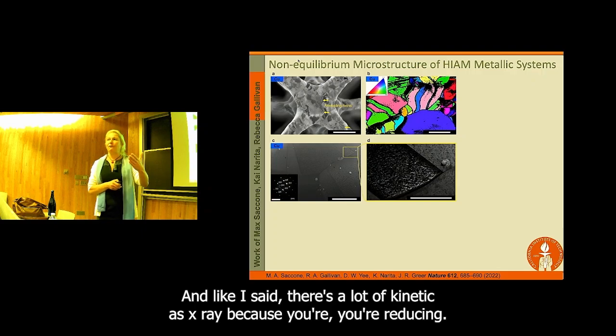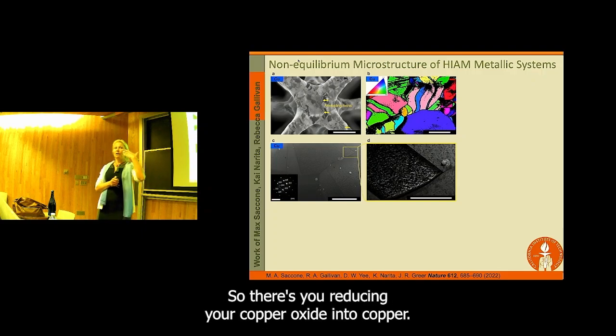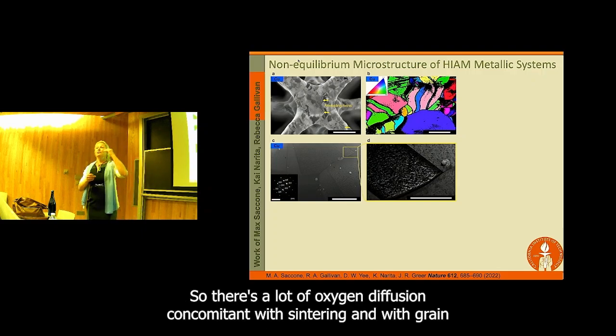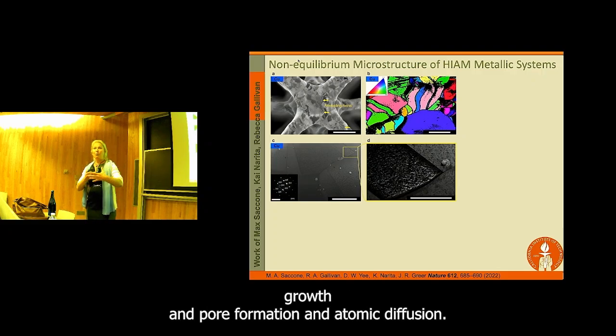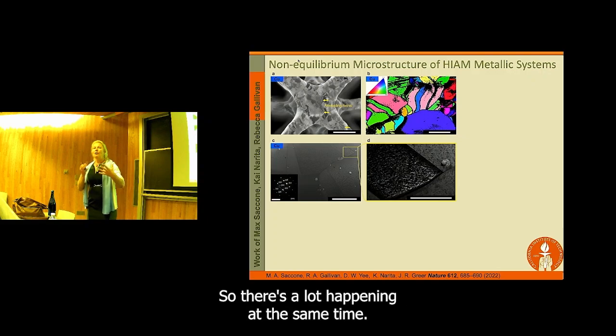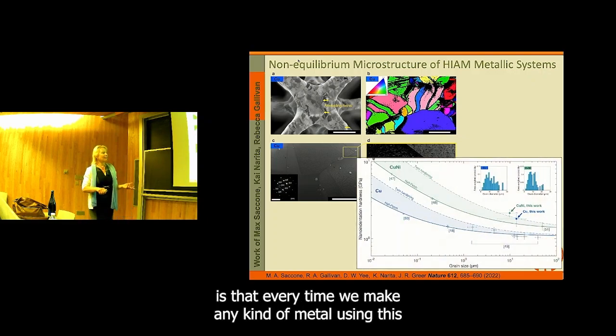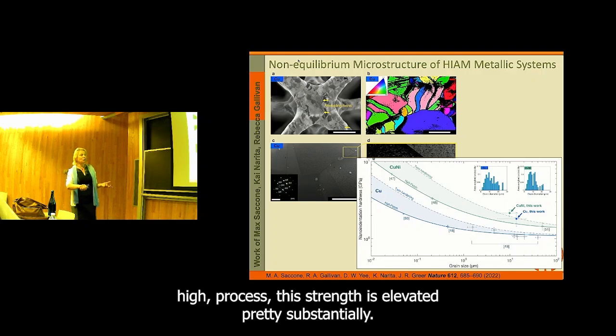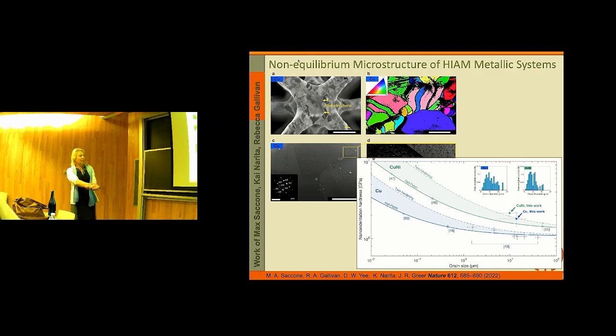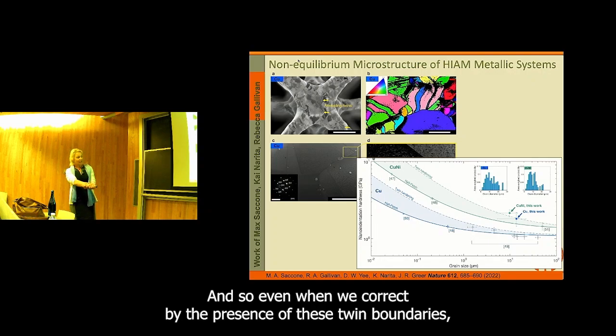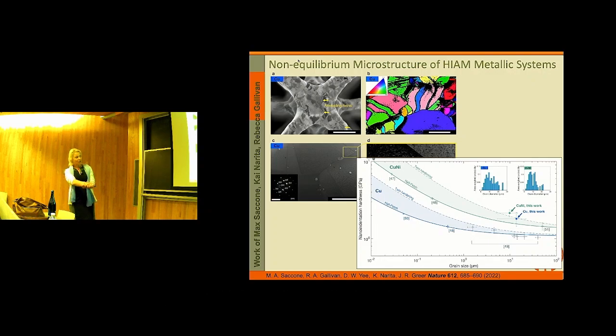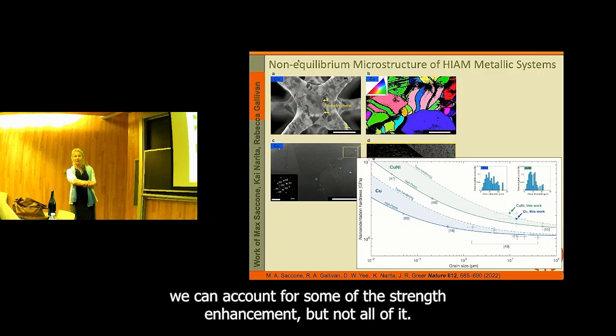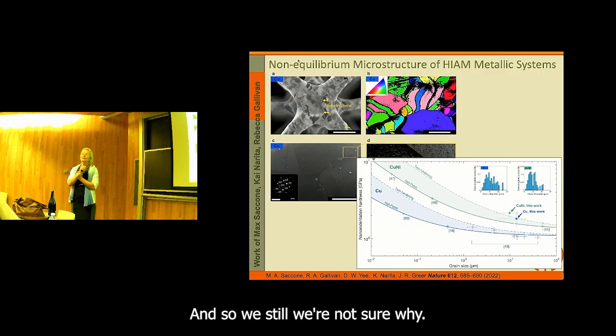And like I said, there's a lot of kinetic effects, right? Because you're reducing your copper oxide into copper. So there's a lot of oxygen diffusion concomitant with sintering and with grain growth and pore formation and atomic diffusion. So there's a lot happening at the same time. And so what we've learned is that every time we make any kind of metal using this HIAM process, the strength is elevated pretty substantially. And so even when we correct by the presence of these twin boundaries, we can account for some of the strength enhancement, but not all of it. And so we're not sure why.